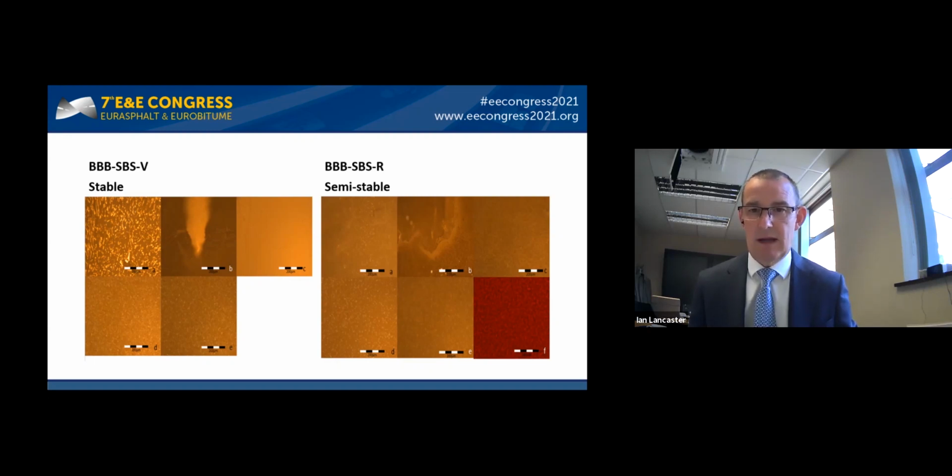Here we have a stable and a semi-stable binder. The results, though, are really rather similar. In both cases, we get a coarse dispersion in our standard preparation technique, EN13632, and also the fracture surface technique. However, again, the direct application techniques, spot annealed and hot casting, show very little changes in the case of the stable binder and subtle changes only in the case of the semi-stable binder. So this gives us evidence that those direct application techniques are a potential indicator of storage stability.